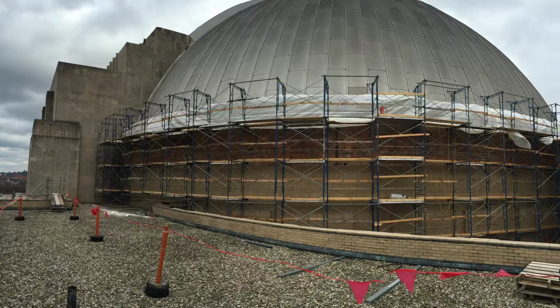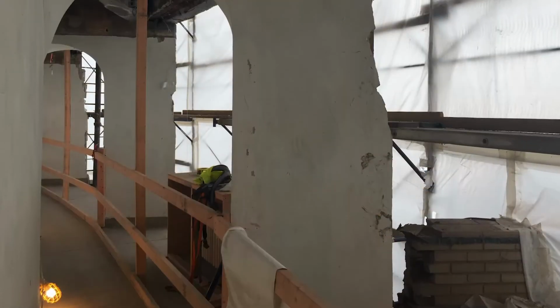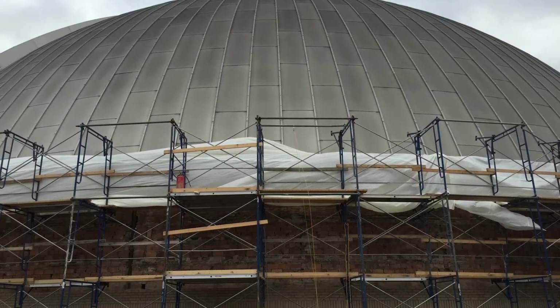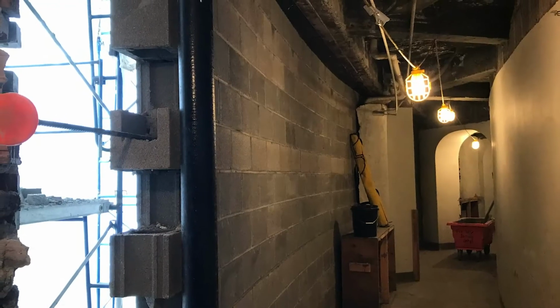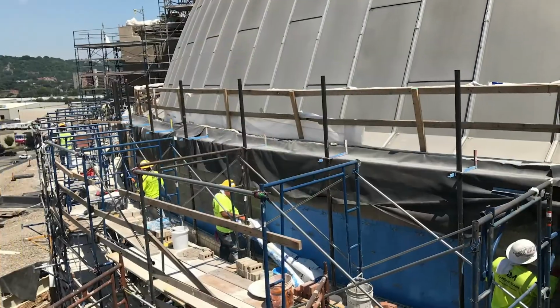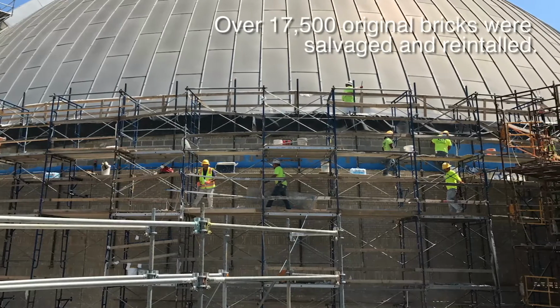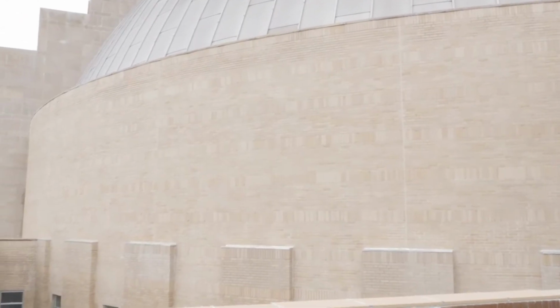One of the most significant masonry and structural projects was the rebuild of the curved drum walls that sit just beneath Union Terminal's half dome. Outdated construction techniques and the lack of expansion joints resulted in poor thermal expansion capabilities, damaging the wall system. The drum wall was completely disassembled and rebuilt between January 2017 and February 2018, replacing the interior terracotta wall with a concrete block wall supported by steel rods woven throughout. As a final step, original exterior brick was applied over top the reinforced concrete wall.